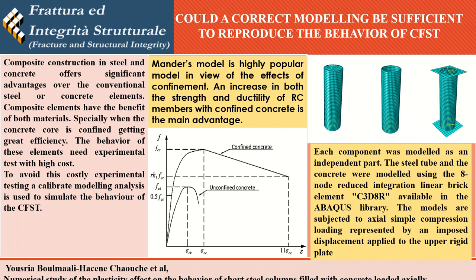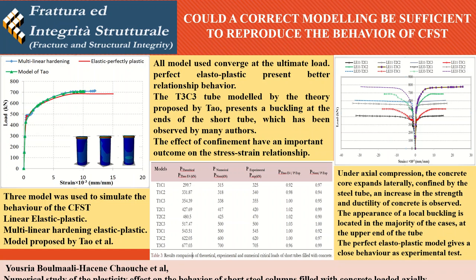All of the models converge at ultimate load. However, the perfect elastoplastic model presents better behavior. All three tubes show local buckling. The barrels follow a non-linear elastoplastic behavior, with the highest lateral strain value corresponding to the T3C3 tube modeled by the theory proposed by Tao, reaching 25% with local buckling at its end, which has been observed by many authors.